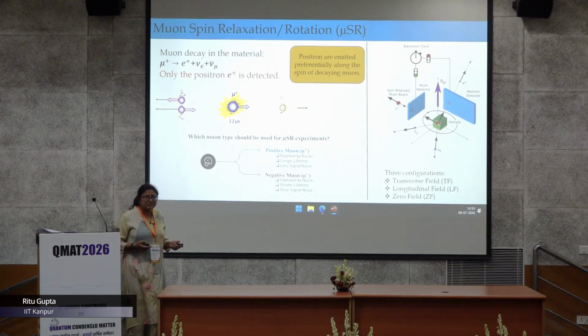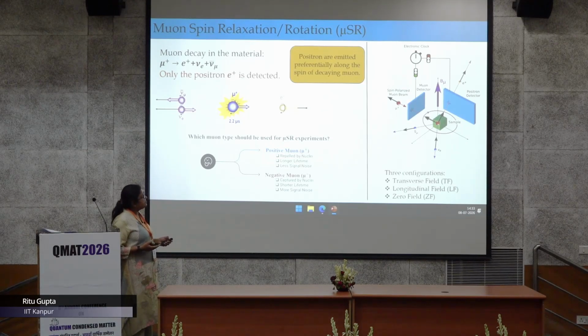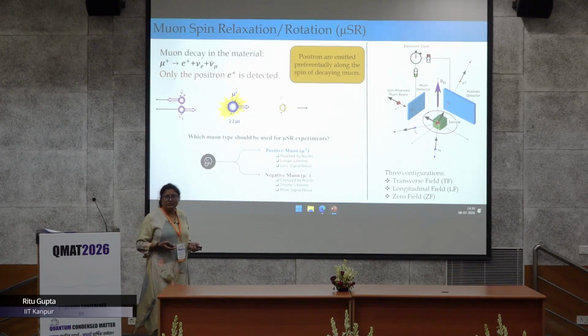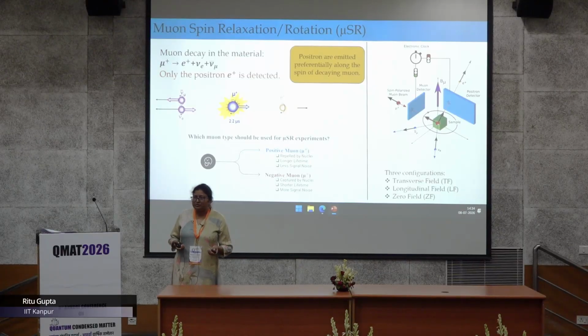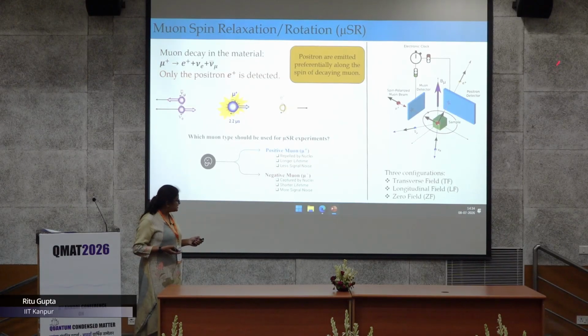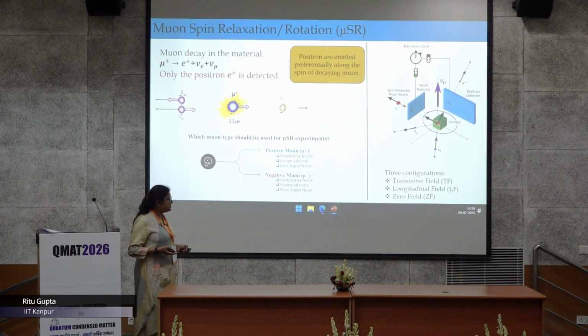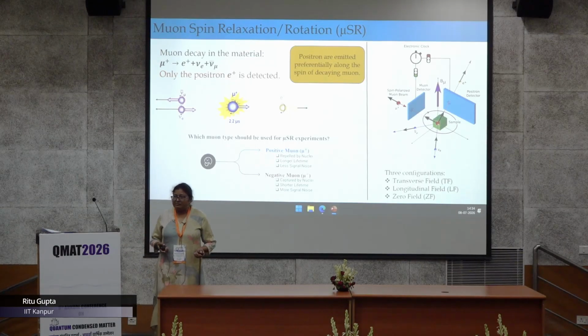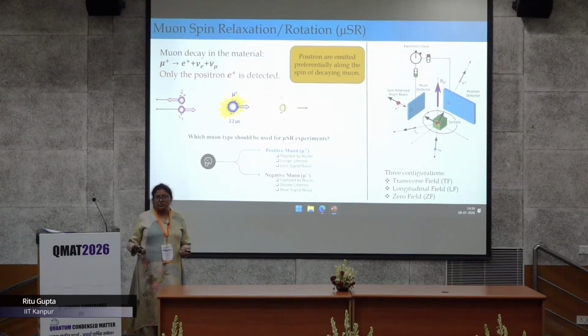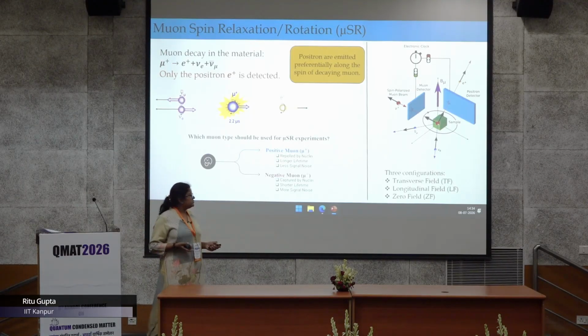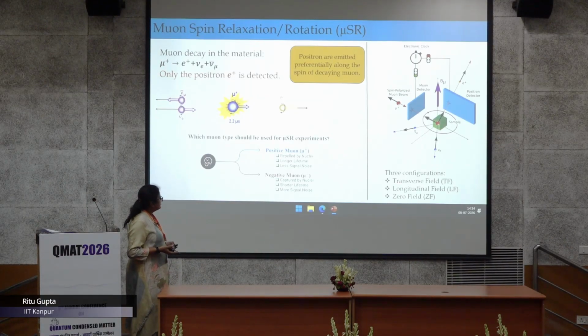Basically you can do measurements in three different configurations. In one case you apply a magnetic field perpendicular to the muon spin direction, in one case you apply it parallel, and in the third case you do not apply any magnetic field, you do the experiment in zero field. These types of experiments are important when you are looking for very tiny magnetic fields. For example, if you are looking in a superconductor for some internal magnetic field because of time reversal symmetry breaking. So these are the three configurations.